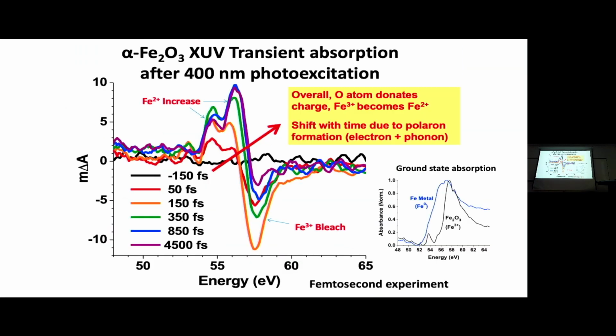And first of all, look here. This is the Fe2O3, the normal absorption in the XUV. And it's around, say, 60 electron volts. And we know in Fe2O3, if you make it correctly, it's all iron 3 plus. And this is the neutral metal. So you could see that there's a big difference between the 3 plus and the neutral metal. And in addition, there's a big difference between 3 plus and 2 plus.